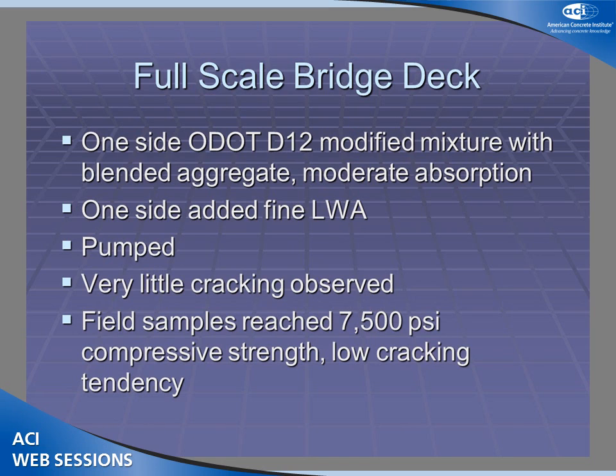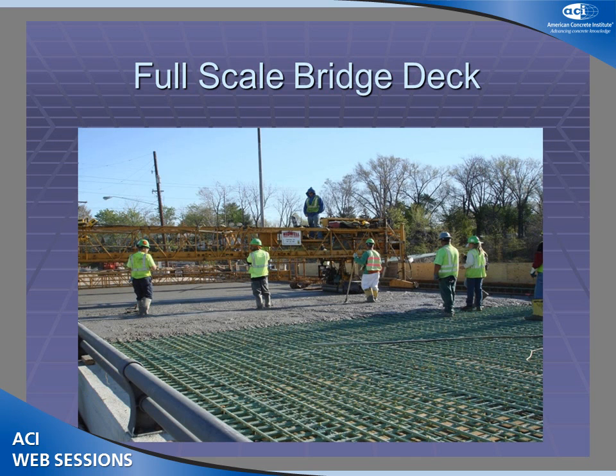Their HP bridge deck mixture is really designed on a durability, permeability type basis. Their required compressive strength is 4,500 psi, and they routinely blow by that by 2,000 to 3,000 psi, which really isn't all that relevant for a bridge deck because how many times have you seen a bridge deck fail in compression? It's always durability issues that get it one way or the other.